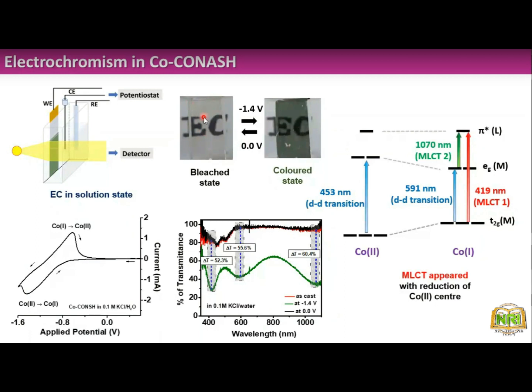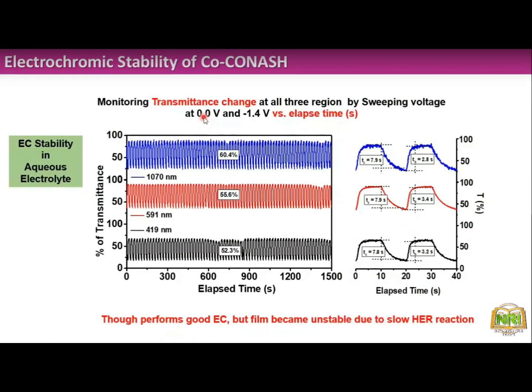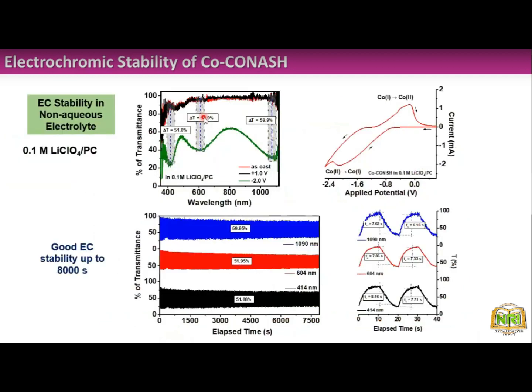Okay, so to avoid this, because obviously water is there, that's why the water splitting reaction is happening. So what if we change the electrolyte? Next, what we did, we changed the electrolyte and used a non-aqueous electrolyte, which is propylene carbonate. The electrolyte is lithium perchlorate.